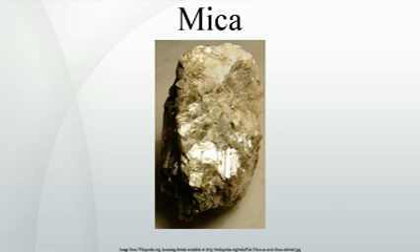Atomic force microscopy. Another use of mica is in the production of ultraflat, thin film surfaces, for example gold surfaces, using mica as substrate. Although the deposited film surface is still rough due to deposition kinetics, the backside of the film at the mica-film interface provides ultraflatness when the film is removed from the substrate. Such ultraflat substrates are common substrates for sample preparation for atomic force microscopy.